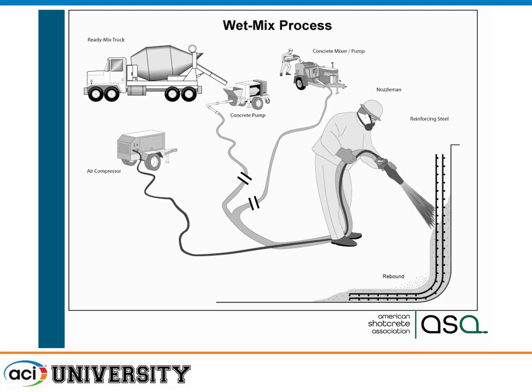And if you're seeing good shotcrete going in place, it shouldn't be a 125 CFM compressor. Probably about a 185 would be the least that should be used for shotcrete, because we want that high volume, high velocity projection from the nozzle. If it's dry mix, we actually go up to probably about 500 CFM compressors.